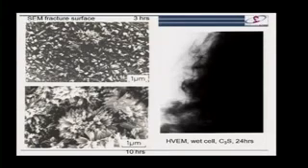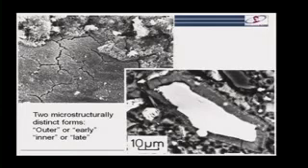So this is 3 hours hydration, this is 10 hours hydration, this is the surface of a C3S grain, and you see on the surface of the C3S grain we start to form these little pockets of CSH. They're growing, and then at a later age we form this dense, what we call inner product. Well, why do we call it inner product? Because if you trace this initial outline like this, we think this more or less represents the outline of the original grain. So this dense product here is formed inside the original grain. This filamenty product here is formed outside the original grain.